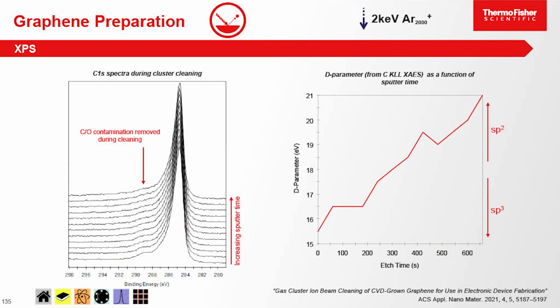So what we can do then is clean the sample using the MAGCIS cluster source. If we go any higher than the lowest beam energy and go to a smaller cluster than 2,000 atoms, you damage the graphene. It just breaks it apart. You have to be really, really gentle with this stuff to clean it up. And then we remove the contamination. So this is the surface, and then as we etch away, this peak disappears until we get something that just looks like that asymmetric tail we'd expect on the graphene.